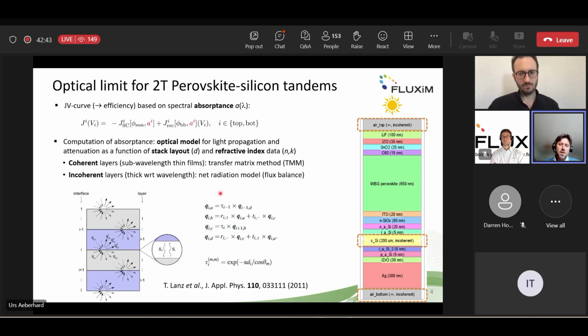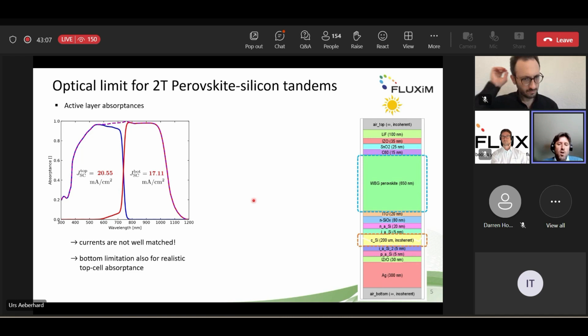what we use here is a kind of ray optics model that is based on the balance of the fluxes incident on different parts of the device. So if you have an interface, you have to make the balance of incident and outgoing fluxes. Now we have the combination of these two models for the propagation of incident light through our device to compute the absorptance in the active layers. And you see here that this really deviates from the unit step absorptance, even though it's actually quite close to 1 in a significant part of the spectrum that is absorbed.